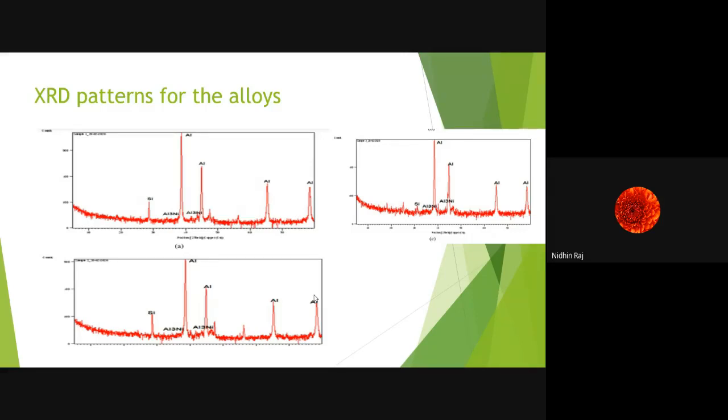The Al3Ni intermediate phase observed for all the alloys in the current study was found to be in accordance with the XRD analysis conducted by previous studies. Hence, it was concluded that the Al3Ni phase is forming in all the conditions that are being discussed in this investigation.